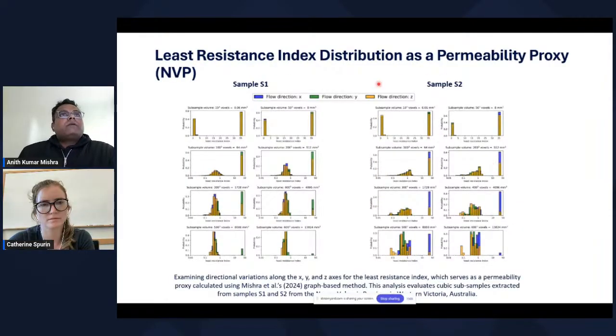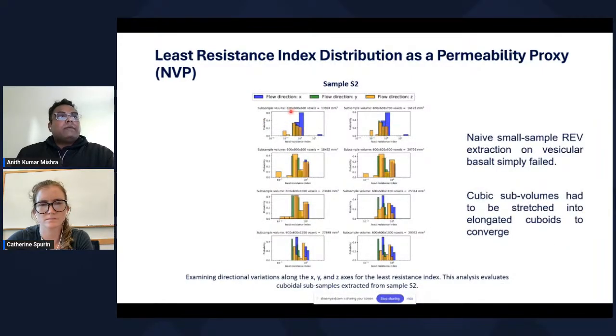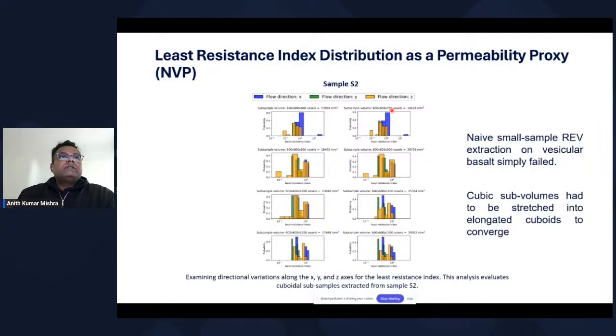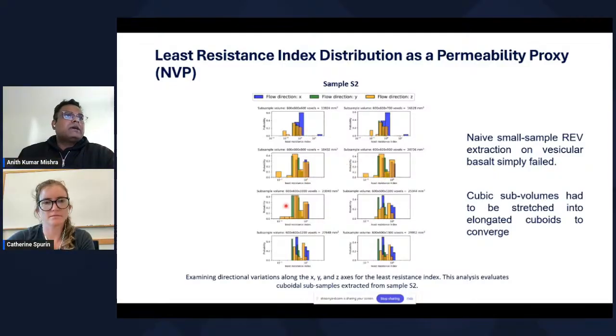We tried to do that for permeability, and for permeability we actually used the least resistance index using the reduced physics flow. Here, we did not find permeability convergence even at 600 cubic voxels. You see one outlier present here, and the same for the other sample as well. So we could not establish a least resistance index for permeability for the Newer Volcanic Province basalts. Then we kept the X and Y dimensions at 600, but kept increasing the Z dimension from 600 to 1300. When we started increasing that, we could see some sort of convergence around 900 or 1000 voxel levels. So the key takeaway is that the cubic subvolumes had to be stretched into elongated cuboids to converge. Otherwise, we could not see convergence.